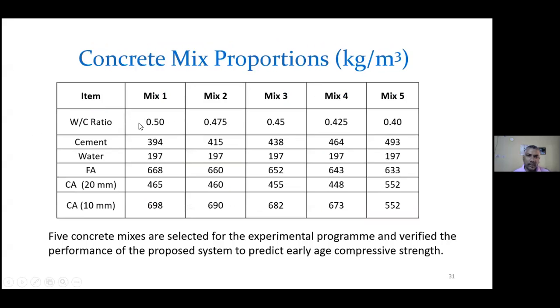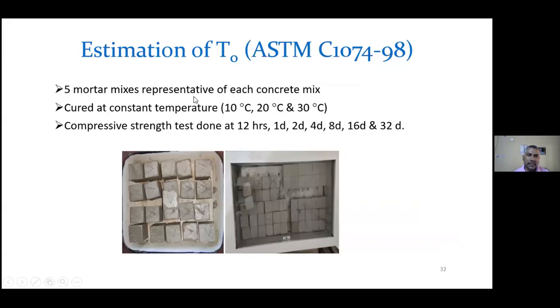Corresponding to the 5 concrete mixes, 5 mortar mixes are prepared, right? 5 mortar mixes representative of each concrete mix, where, as I discussed, the cement to aggregate ratio and the water to cement ratio are kept constant. They are cured at 3 constant temperatures: 10 degrees, 20 degrees, and 30 degrees. And the compressive strength test, the break test, right? The specimens are broken in a compression testing machine at 12 hours, 1 day, 2 days, 4 days, 8 days, 16 days, and 32 days. So that is the first thing done.